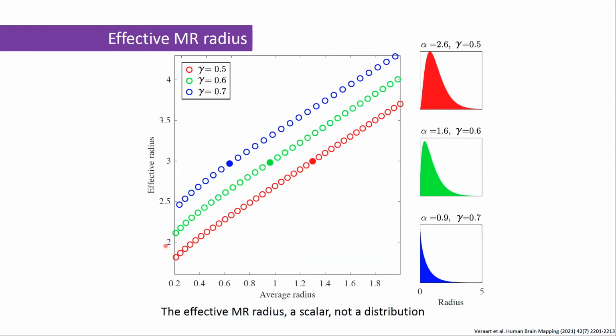A question I often get is: well, if we can measure this effective radius, can we invert this problem and extract the average radius? Because average radius is something that we get from histology, and we would love to compare histology and MR. So can we map the effective radius back onto the average radius? And the answer is no.